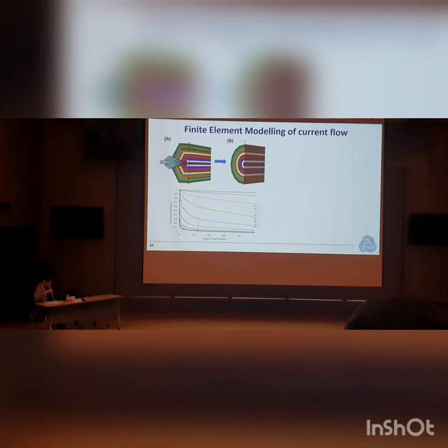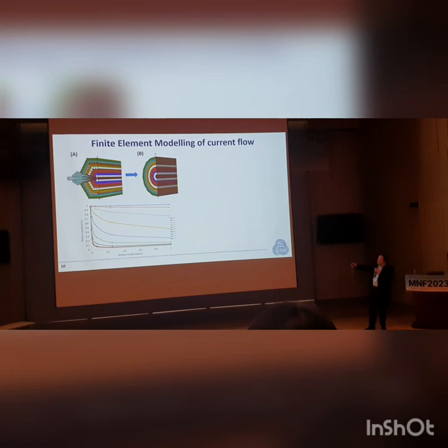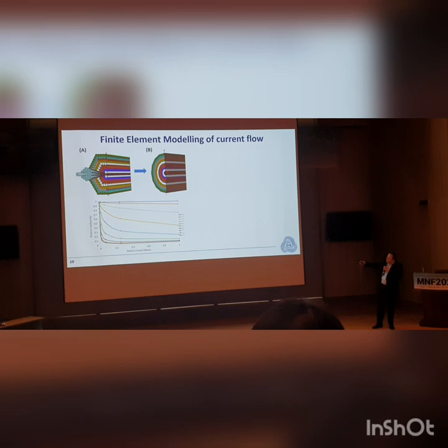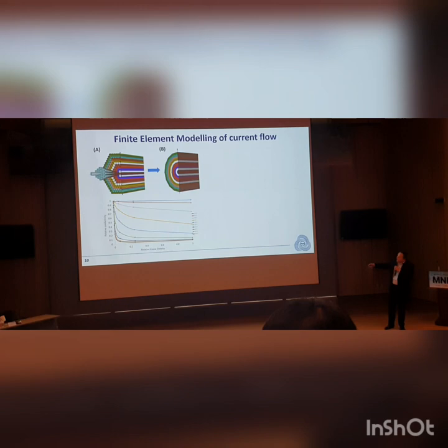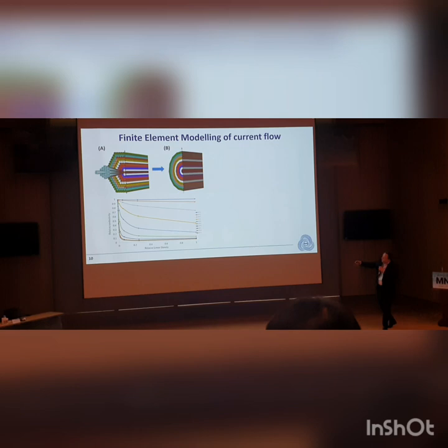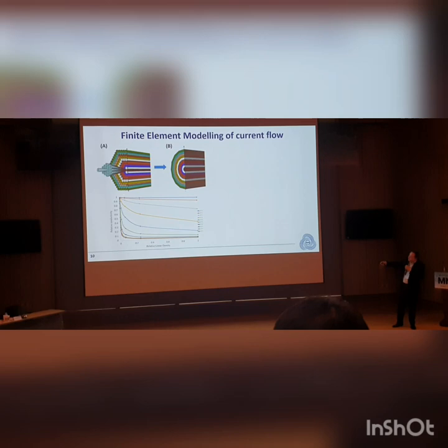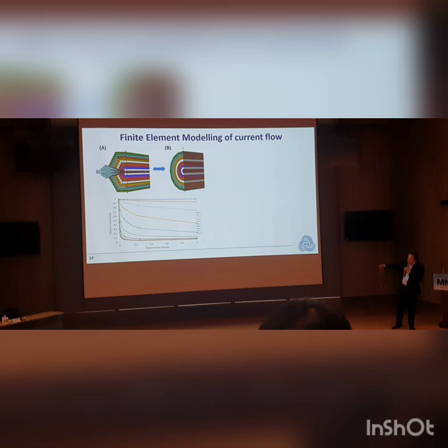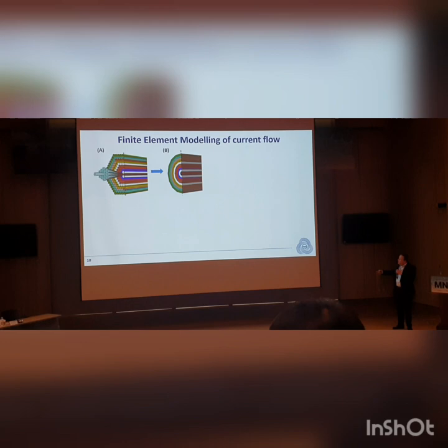We can understand why that happens from modeling. One of my students, Philip McKeown, set up a simple finite element model where bundles are treated as concentric cylinders. Reducing this to an axisymmetric cylindrical model, each colored cylinder represents a bundle surrounded by other bundles. As you increase relative density, the relative conductivity compared to a single bundle drops off. When the conductivity is completely isotropic there's no drop-off, but because these structures are much more conductive along the fiber direction than in the transverse direction, conductivity drops significantly as linear density increases — which matches what we see experimentally.